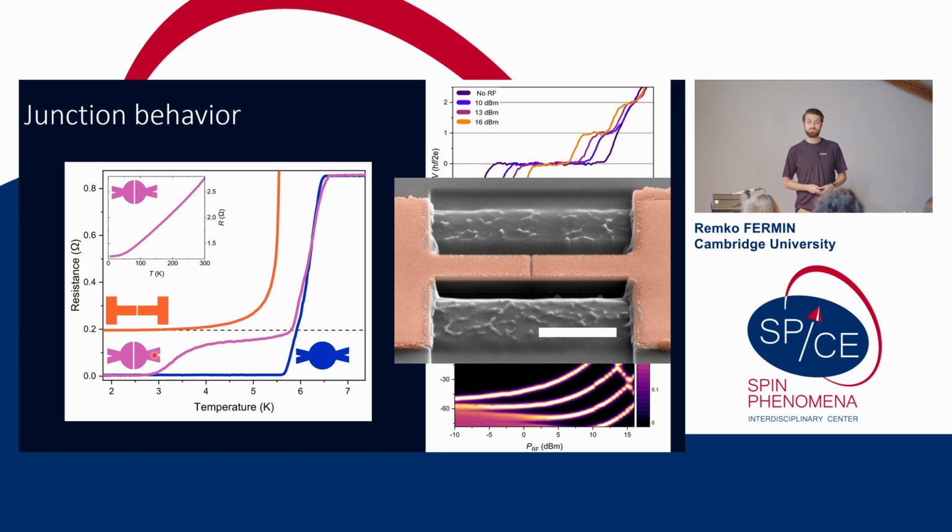We found that these devices have an initial transition corresponding again to the superconducting contacts, but at lower temperatures the resistance flattens out, and the residual resistance at low temperatures exactly corresponds to the resistance value where these two curves part, meaning we are measuring only the resistance of that weak link, which doesn't go superconducting.